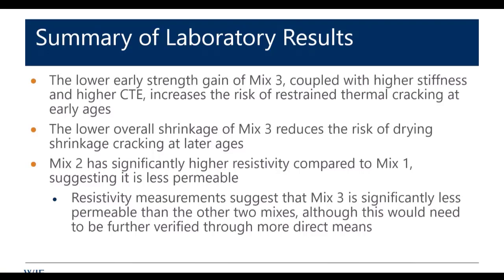Okay, I didn't show the CTE results, but actually the CTE of mix 3 was higher by probably 20% or so. We had lower overall shrinkage in mix 3, and then with mix 2, we saw that jump in resistivity, which we would suggest means less permeability. It's going to help us keep chlorides out. The off-the-chart number with mix 3, I would say, is suspect until we could squeeze pore solution out of it, which we're not going to do unless somebody wants to squeeze some pore solution out of a specimen for us.